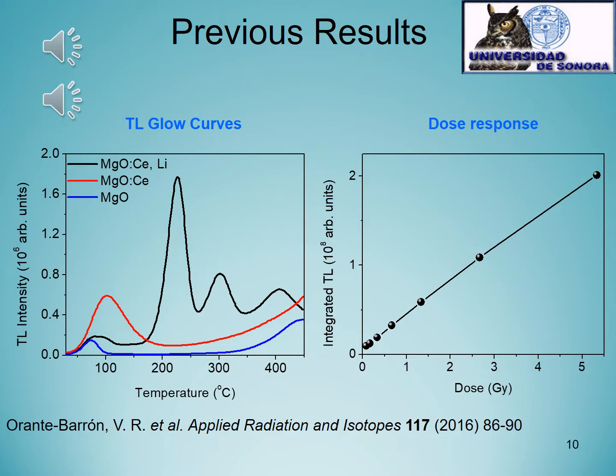If we observe the graph on the right, this is the dose response curve, which has a linear trend within the interval studied of the dose. It is important to add that comparing with the results obtained previously with the urea-based solution combustion synthesis for the same material, we can observe an additional component located at around 400 degrees Celsius.